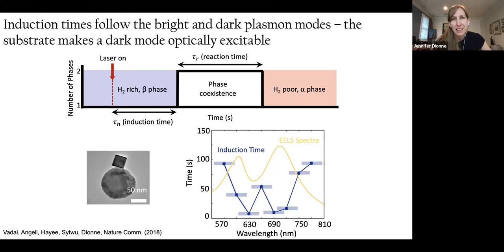What was super interesting about this is the lower energy mode actually corresponds to a dipolar plasmon type resonance. It's optically excitable. You'll also see this mode in cathodoluminescence. But this higher energy mode would normally be dark, meaning you normally wouldn't be able to excite it with light, but by virtue of the substrate, it becomes optically excitable.